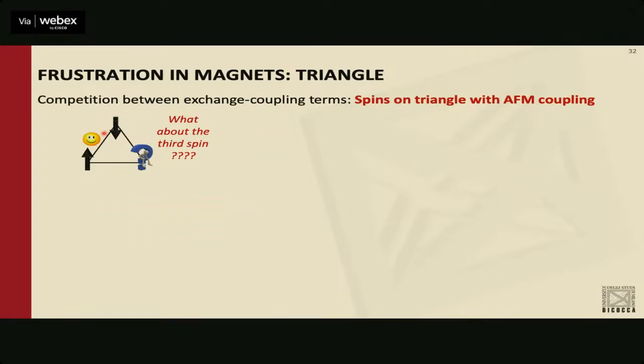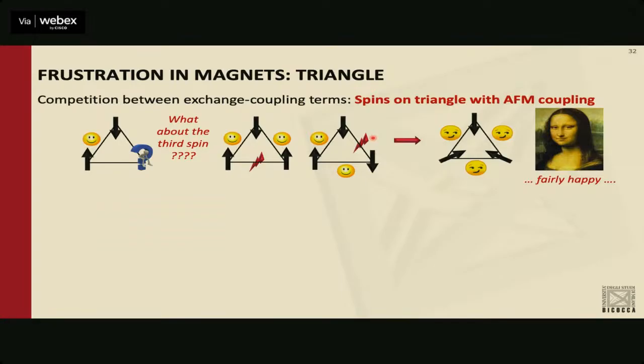So you place your two spins, and this interaction is happy, but then the third spin doesn't know what to do, right? If it lines up, this interaction is not happy, whereas this one is. If you place it down, this interaction is happy, but this one is not. So what the system does is a kind of compromise situation in which it's fairly happy, and it rotates by 120 degrees. So exchange frustration is a very nice ingredient that can give rise to non-collinear spin configurations.